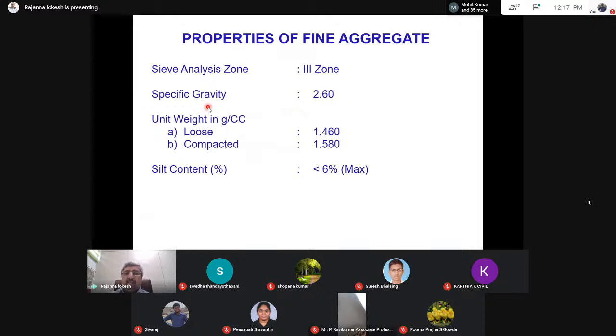Then the fine aggregate, it is proposed to have zone 3 type of sand, where the specific gravity will be around 2.6, and density of loose fine aggregate will be 1.46 gram per cc, and that of compacted will be 1.58 gram per cc. Silt content should be less than 6%.